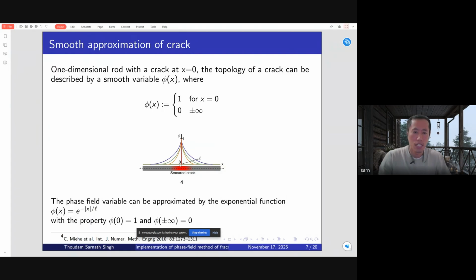This kind of function can be represented by e to the power minus mod of x divided by L. This is not the only function. We can use other functions also, provided that they satisfy this condition: at x equal to 0, phi is 1, and at x equal to plus minus infinity, phi is 0. This function is very commonly used in the literature, but we can also come up with other functions. For my work, I have used this function. So, using this smooth function.